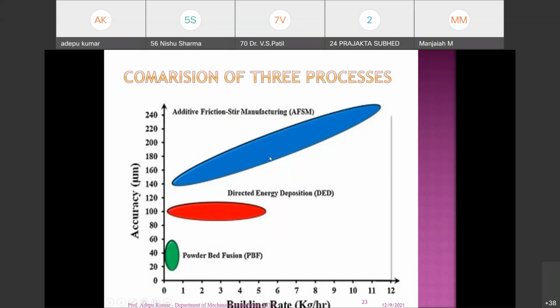Then coming to our additive friction deposition process, or friction stir additive manufacturing process, you can see there is a wide range in building rate as well as accuracy, because within the stipulated time you are able to generate large size components, especially for aerospace applications. The material may be titanium alloys as well as aluminum and magnesium alloys, all done through the friction stir additive manufacturing process. For bullet train panels, people are making panels from titanium alloys, doing friction stir welding as well as the friction stir deposition process. That will give a high strength to weight ratio for high speed trains like bullet trains. So this is the much advantage when you are talking about accuracy as well as building rate with respect to the additive friction stir manufacturing process.